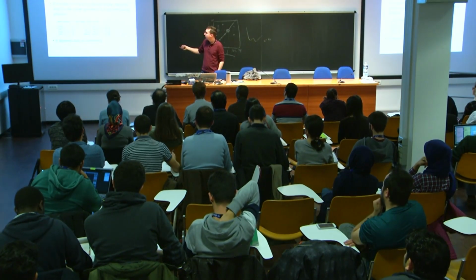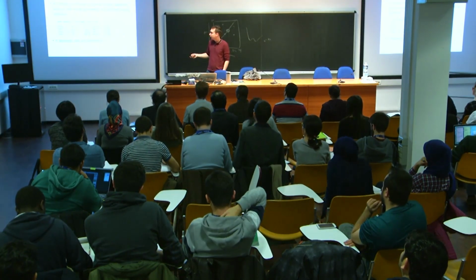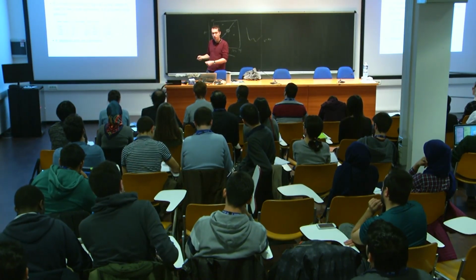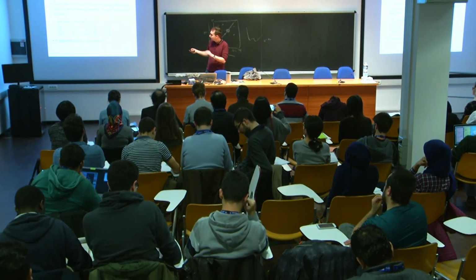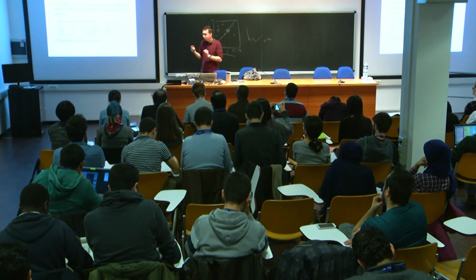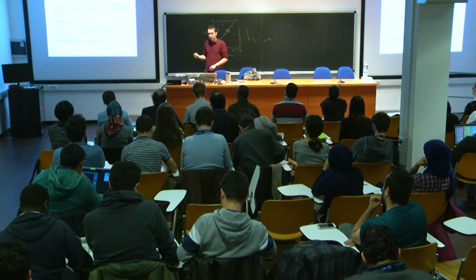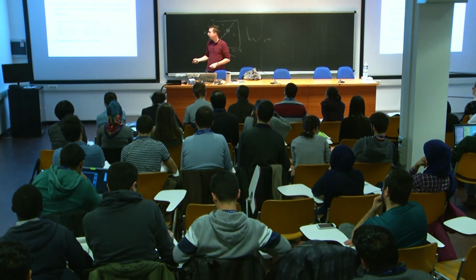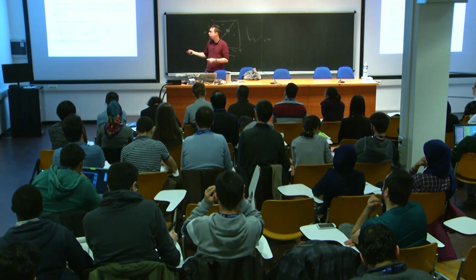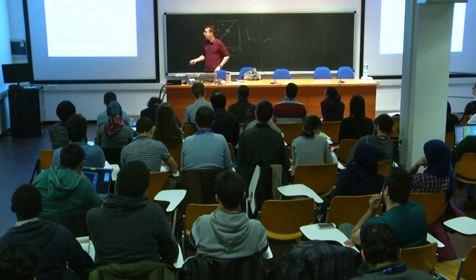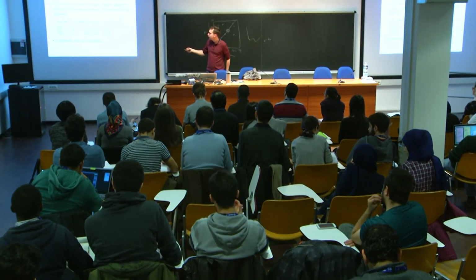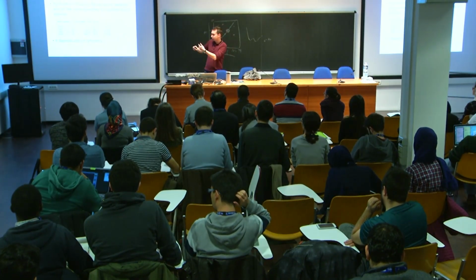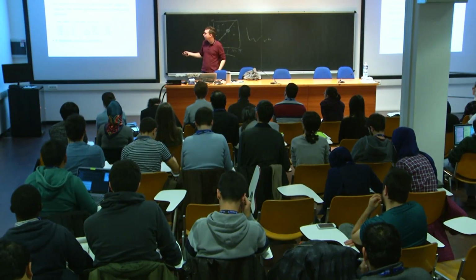The first is the symmetry of the mode, which is important because experimentalists like to use these names when they talk about one mode or the other. Although they are sometimes a bit tricky because, especially for two-dimensional materials, experimentalists like to use the name of the peak in the bulk material to refer to the peak in the layer, but the symmetry of the layer is different, so the symmetry group is different, so the actual mode is different. Sometimes the capital letter is the same and only the rest changes. Sometimes everything changes, so you need to go to the bulk and compare the frequencies to see what they're actually talking about.